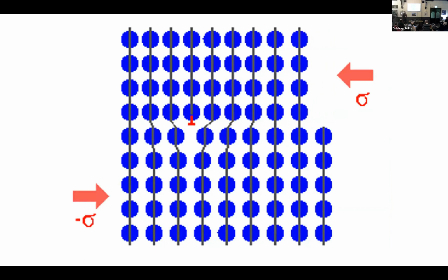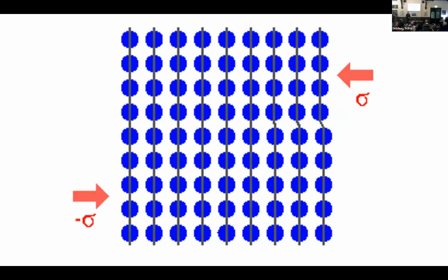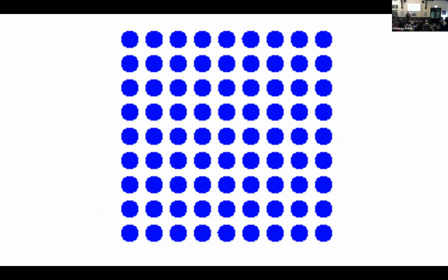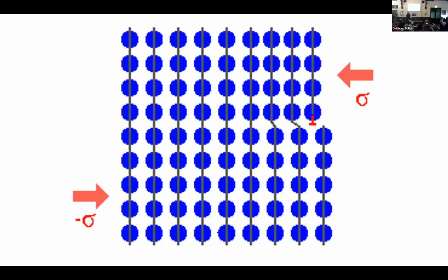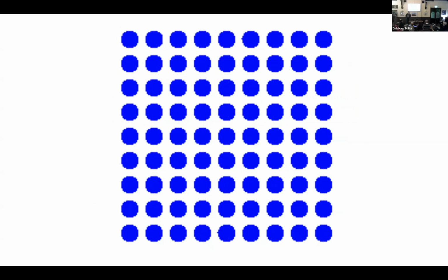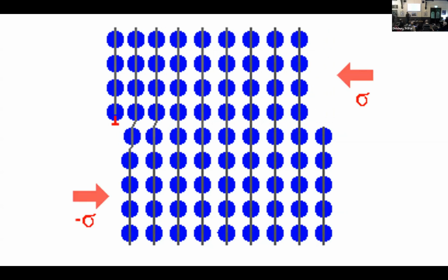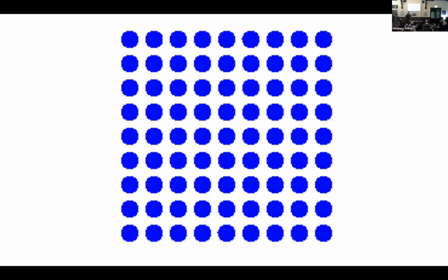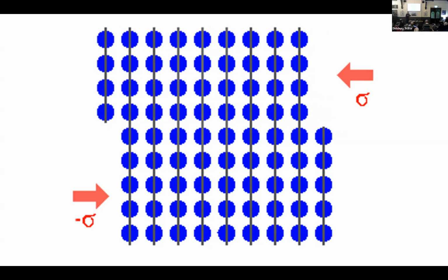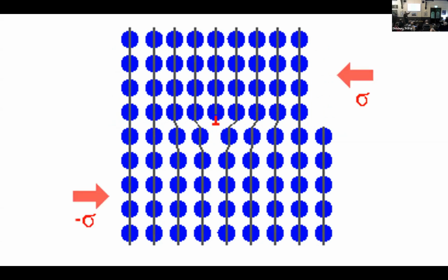Essentially, when the material moves, the atoms move across like a wave. The way you can think about this is, imagine this book, where each page is a series of atoms. If I take one more plane of atoms and jam it in there, I create what's called a line defect. You can see the page that runs through, and basically it forms the shape of a line. These lines move, and as we apply stress to our material, these lines move across, and this is actually the mechanism that's responsible for transporting our material across and forming that dent when we've hit it, essentially.